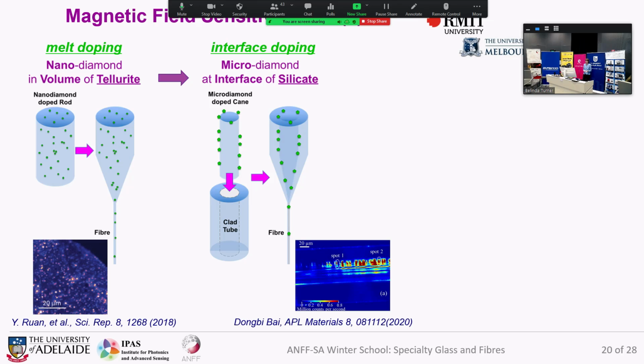During fiber drawing we have a higher glass viscosity, and we couldn't see any sign of damage to the diamond microparticles.